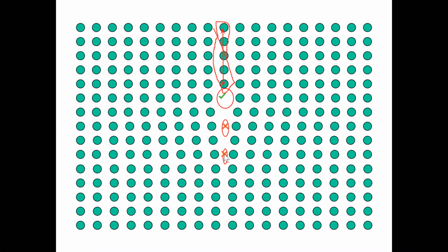It is because at the edge of the extra half plane, where the extra half plane ends, you have the highest amount of distortion. So if you look at the entire lattice, the point where the extra half plane ends is where the highest distortion in the lattice takes place. And that is why we refer to that particular location as the location of the defect and not any other position.